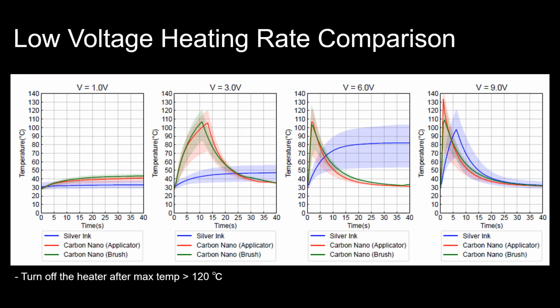This graph shows the heating rate of the silver ink heating circuit and the carbon nanomaterial heater at different low voltages. To protect the PET film, the heater was automatically turned off at 120 Celsius degrees. While the average temperature of the heating circuit did not reach 100 Celsius degrees at 6 volts, the carbon nanomaterial heater rapidly heated above it in a few seconds. At 3 volts, the carbon nano heater shows more than 10 times the heating speed of the heating circuit to reach above 100 Celsius degrees. Both brush paint and film applicator show similar heating speed.